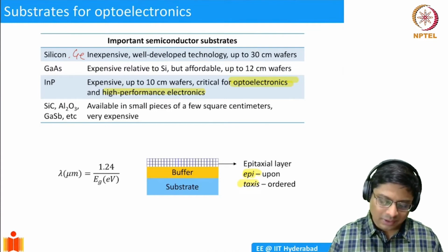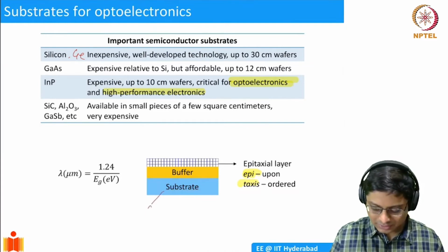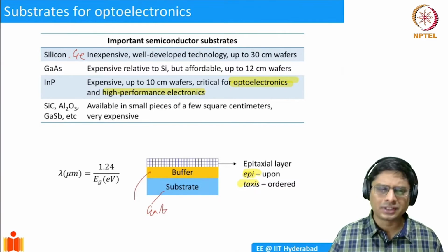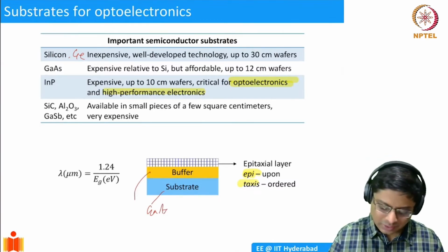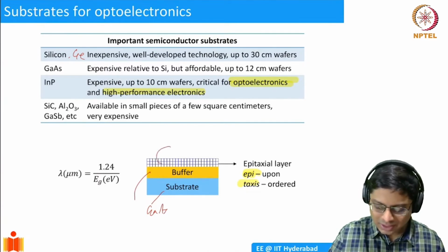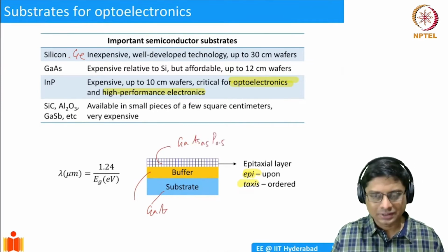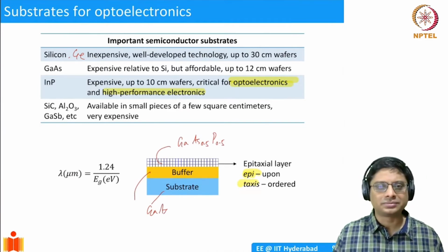So an example would be, take a substrate. I could take, for example, gallium arsenide. Then I grow a buffer layer. This is for growth reasons; for now you can just accept it. It's some sort of combination. On top, the epitaxial layer, I want gallium arsenic 0.5, phosphorus 0.5. If I want that, I need to have a small buffer layer, and then I can grow this material.